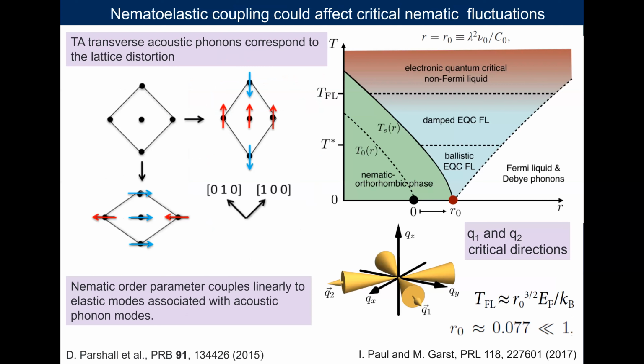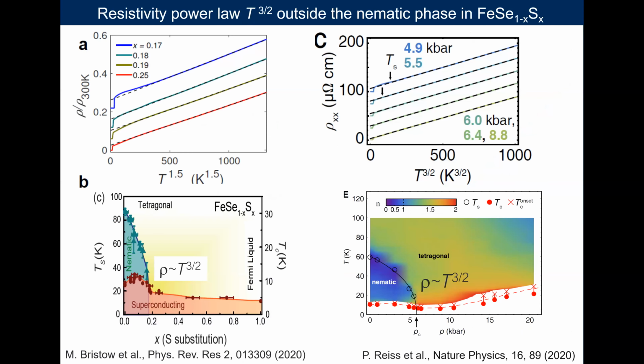So now, why don't we have divergent effective masses at the nematic endpoint, the critical point? One reason for this is that the system has a finite coupling with the lattice. So here on the left, it's been shown that structurally the transverse acoustic phonons correspond to the lattice distortion. And this nematoelastic coupling is likely to affect the critical fluctuations. This is a phase diagram built by Paul and Garst, which shows that the finite coupling with the lattice is likely to shift the position of the nematic critical point in the first place. Additionally, nematic critical fluctuations are only allowed in certain directions. So if we measure a quantity which is orbitally averaged, then we are likely to pick up this effect. So one reason is this finite coupling with the lattice.